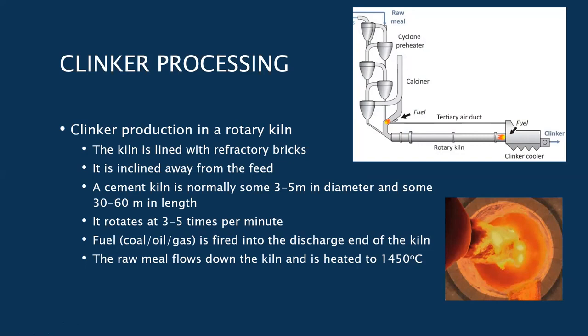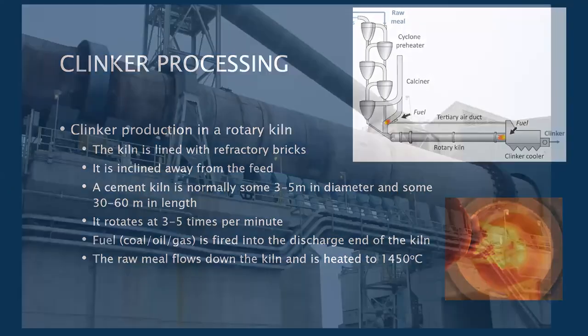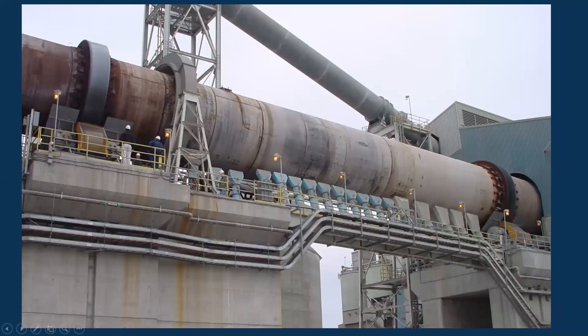The kiln is lined with refractory bricks and it is inclined away from the feed. A cement kiln typically is about 3 to 5 meters in diameter and some 30 to 60 meters in length. It rotates quite slowly at about 3 to 5 times a minute, and it is fueled at the bottom over here by either coal, oil, or gas. In South Africa, mainly pulverized coal. This is blown into the kiln and it creates a huge flame, as you can see in the bottom right-hand corner. The raw meal, which is fed in the other end, then flows slowly down this kiln and gets heated up to 1,450 degrees centigrade. It's an idea of what a kiln looks like. You can get some idea of the size by the humans standing over here.